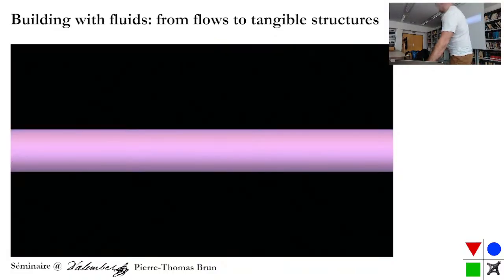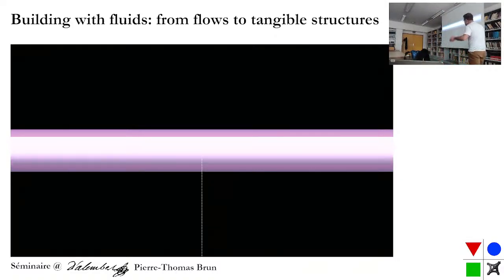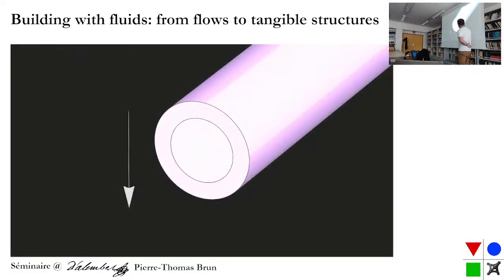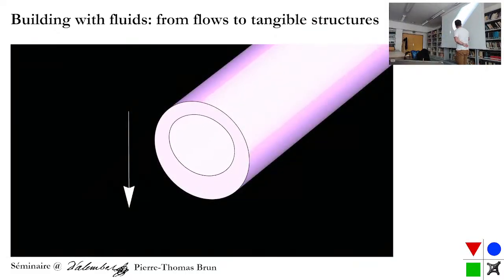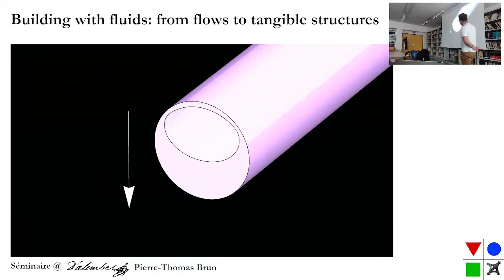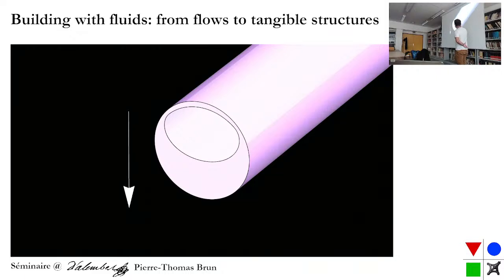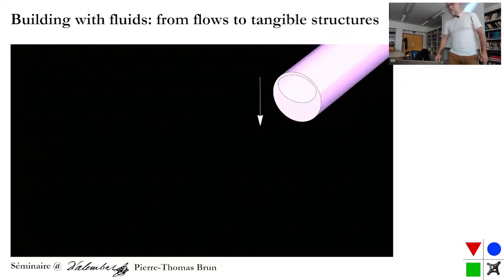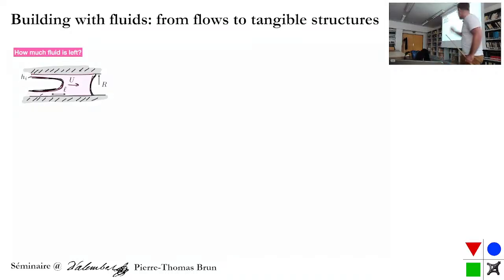Okay, so this is my cylinder. I push a bubble. I'm carving this cavity, a Bretherton-like flow. I have initially a cavity that sits in the middle, and as time passes, the fluid drains or the bubble rises, and then eventually I get something that looks like that, which is now elastic. And so if I inflate it, this will deform more than that because it's thinner. And so if you have this excess of length, you will actually move in one direction. Okay, and do that.